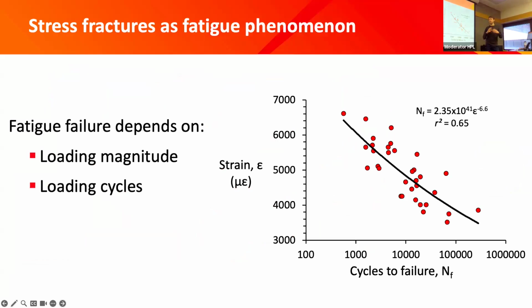All right, so in our lab, we like to try and quantify stress fractures as a fatigue phenomenon. So what does that mean? Well, if we go back to our example of the paperclip, essentially we can track the magnitude of load that we're applying to that tissue, in this case bone. We can also track how many cycles that bone lasts until it fails. So this is some data from fatigue tests of bone. On the y-axis, we have the strain that we're loading that bone at, and on the x-axis, we have the number of cycles that the sample lasts.